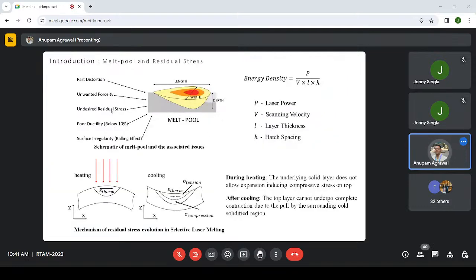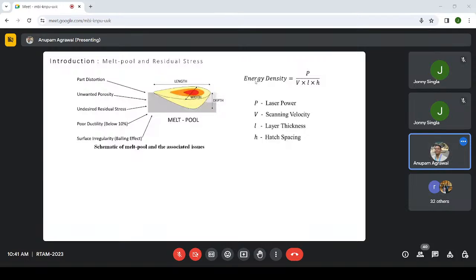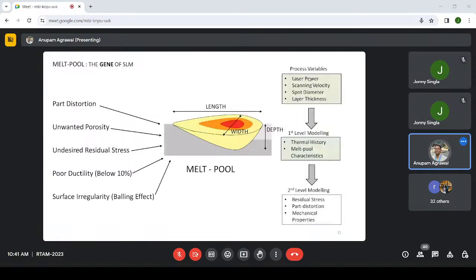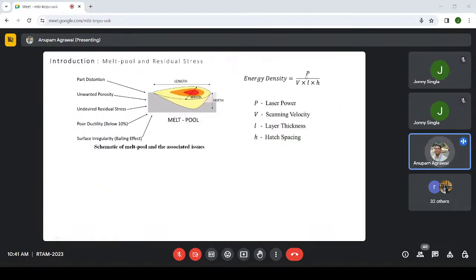So as we said, this melt pool depends primarily upon the energy density, because this is the first, the laser power. So it depends upon the energy density, P divided by V into L into H. V is the scanning velocity, L is the layer thickness, and H is the hatch spacing between the two laser scans.